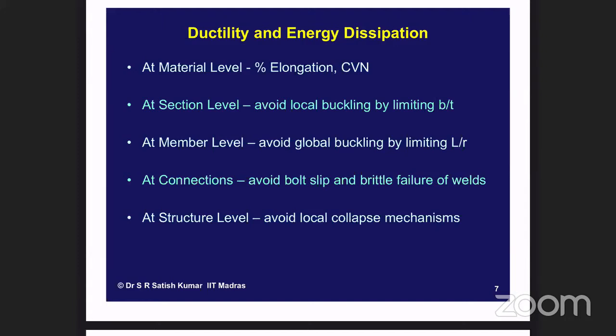The other important property, because earthquake loads are generally impact-type loads, is this: when a material experiences a sudden impact, sometimes a ductile material breaks in a brittle manner. To check this, we do an impact test called the Charpy V-notch test, the CVN you see here. If we do that test and ensure that the steel has adequate energy dissipation capacity, around 21 to 26 joules, then again we can call it ductile. These two properties are related, in the sense that the more energy you dissipate, or the more you work harden, the steel ductility reduces. So we need to make sure that the steel has both elongation ductility as well as energy dissipation capacity.